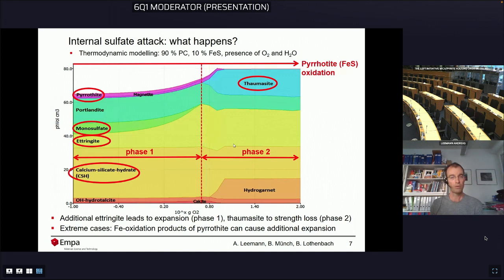But it doesn't end there, because still more sulfur is released. And when all the monosulfate is used up, you start with phase 2. A new mineral is formed. To the upper right, you see thaumasite. Thaumasite is a very soft mineral. You can smear it between your fingers. And thaumasite forms at the expense of calcium silicate hydrate, the CSH. And CSH is the phase or the hydrate that gives the concrete its strength. So the second phase is connected to a strength loss of your concrete. In extreme cases, the iron oxidation products may add to this expansion, but the main issue here is the minerals that form by the sulfur release.